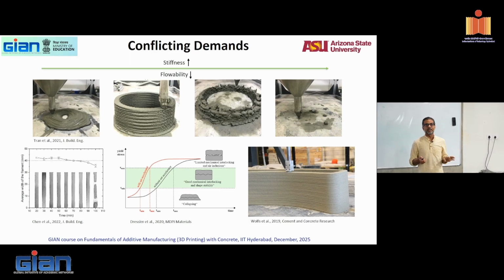Okay, we talked about conflicting demands of stiffness and flowability. Again, stiffness or modulus. You want the modulus to be higher and higher and developing fast so that you can build up your layers and build the stuff faster. One of the biggest advantages of 3D printing, if you look at people who are touting this technology, they will say that you can do very fast construction, correct? If you want fast construction, you better build things up fast. And if you want better buildability, you want the material to develop its stiffness faster. Not stiffness while it is sitting in the mix and the nozzle, but stiffness after it has come out of the extruder.